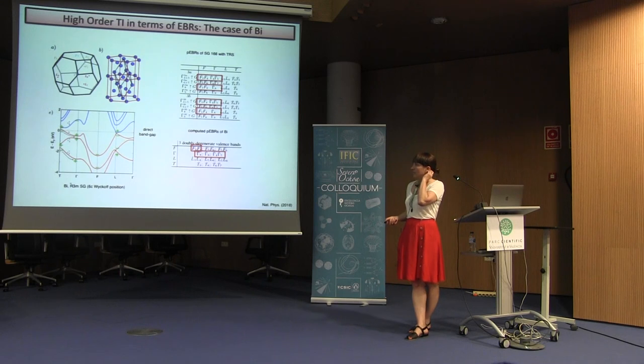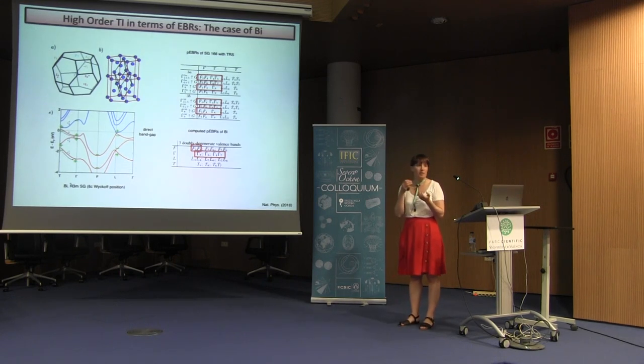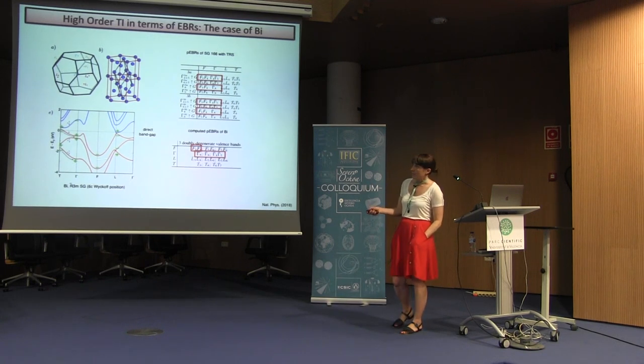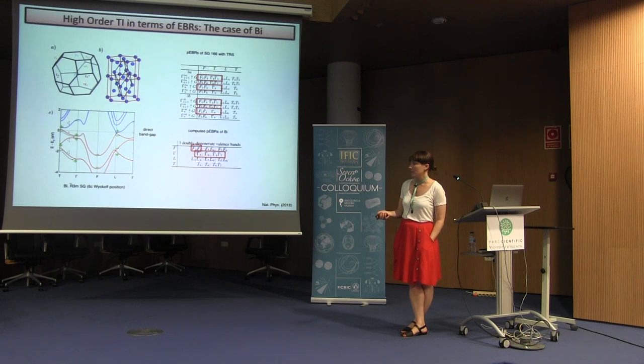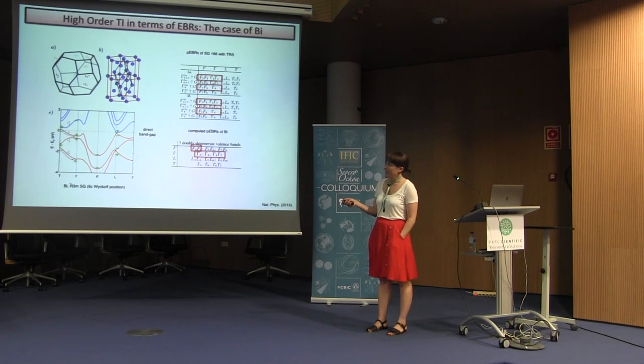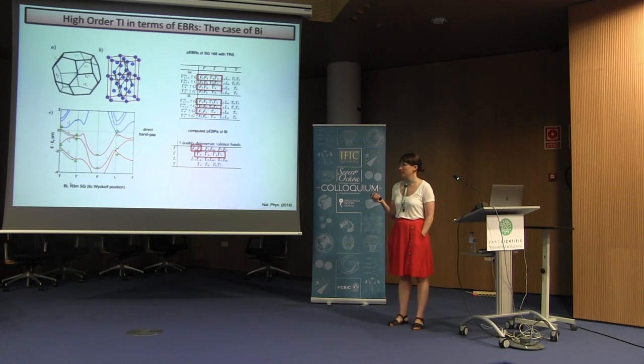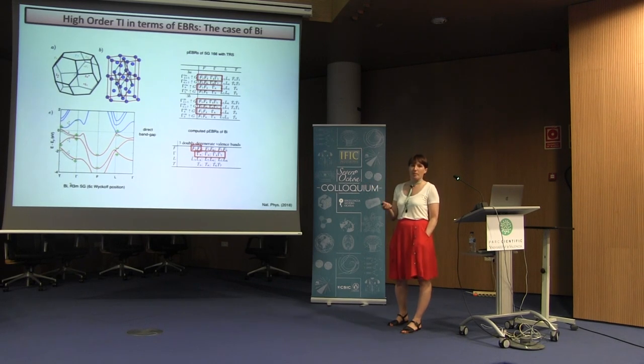But some experimental colleagues told us that they were measuring some quantized current at the edges of this material, and since we had the new method, whether we could check if actually this material displayed topological properties or not. So this is the band structure of this material. It belongs to a hexagonal space group. And in red, we have the valence bands, and in blue, the conduction bands. And if we look at the band structure, it seems that these two peaks could be connected. And maybe they were disconnected because bismuth is one of the heaviest elements and it has a very strong spin orbit coupling.